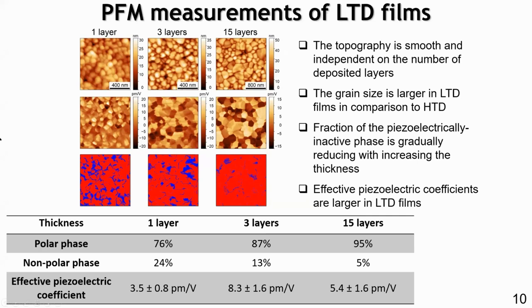And as you may see, the piezoelectric coefficients are also at quite a high level, so it really allows us to postulate that this kind of low temperature and long time drying makes sense for the final topography and morphology of the film. So we can discuss it from the point of view of the morphological changes. When you deposit a film, it makes sense when we do the further annealing at low temperature or high temperature. If we do really high temperature, we have a non-equilibrium process, and we have really fast evaporation of the liquid phase, and this liquid phase